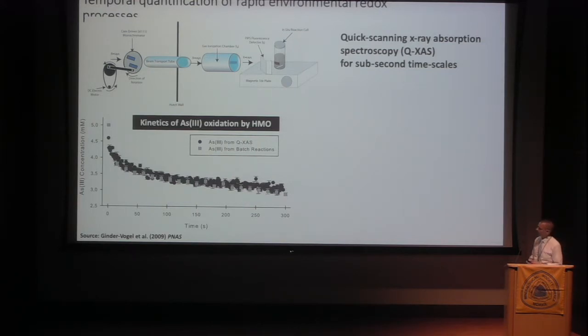So this was a study that looked at arsenic-3 oxidation by hydrous manganese oxides, showing data that could be obtained from the quick XAS in contrast to batch experiments, and getting into the sub-second timescale of the reaction in a way that in traditional bulk experiments we could not get to.